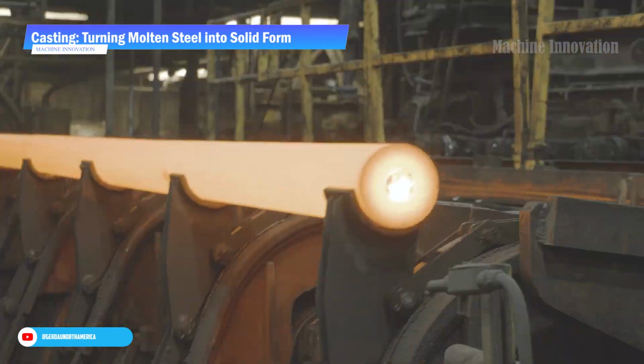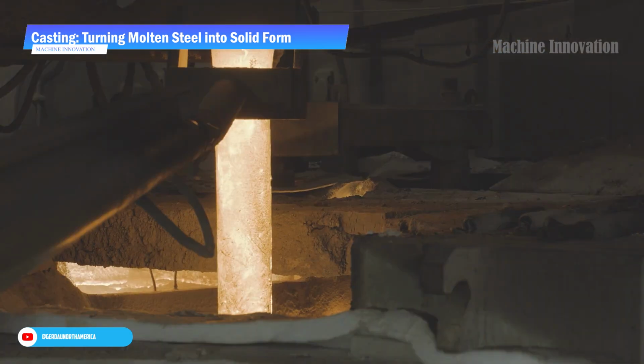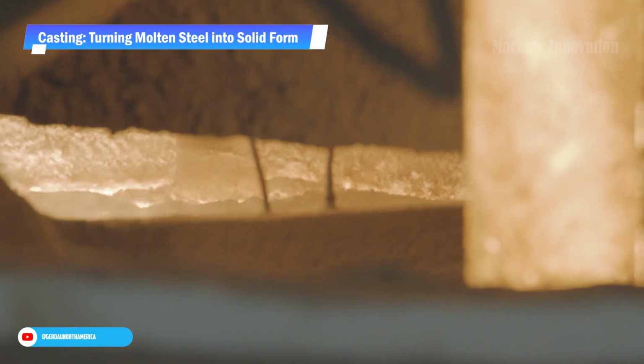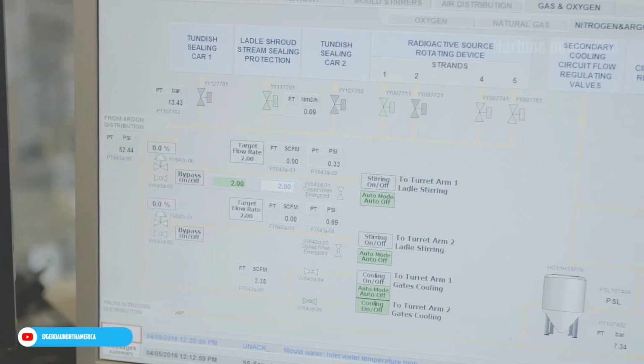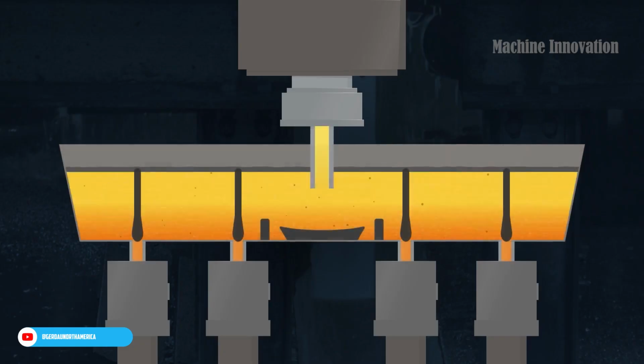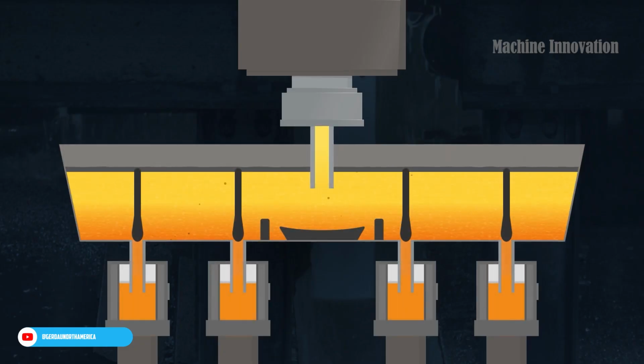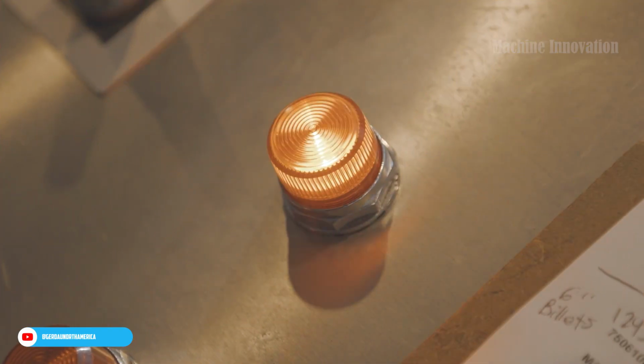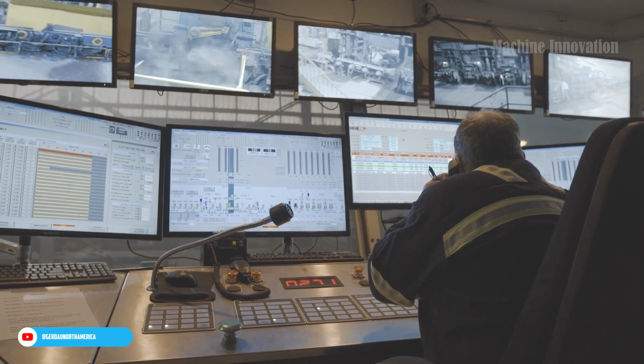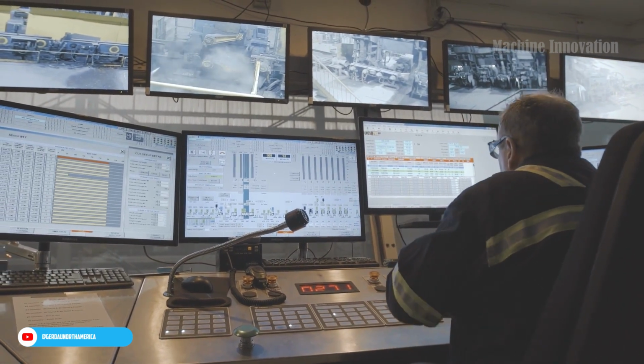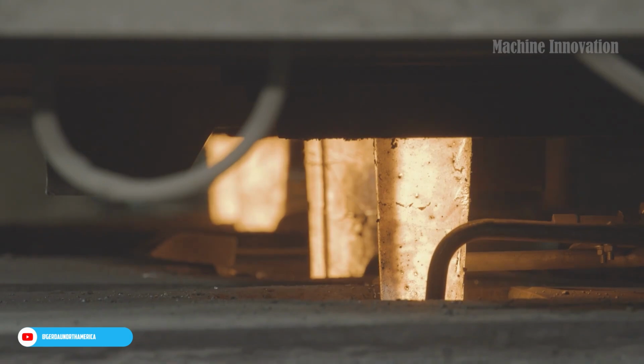Gerdau uses two casting methods, rotary casting and strand casting. Rotary casting. In this method, the ladle delivers the molten steel to a tundish, a distributor that directs the liquid metal into rotating molds. The molds spin, using centrifugal force to push the molten steel against the mold walls, which cools and solidifies the metal from the outside in.